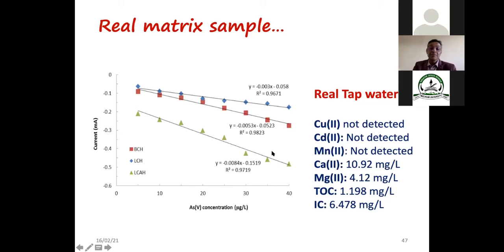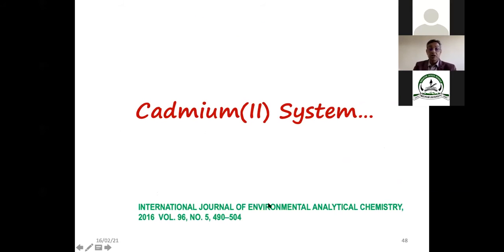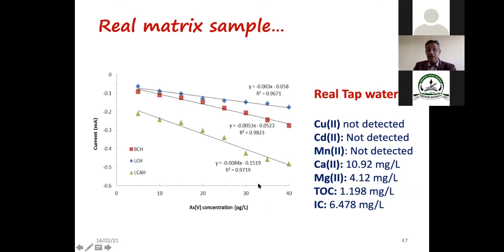If you see, the R square values are 0.98, 0.97, 0.96 like that. So a very good correlation was obtained, whether we have used the organically modified bentonite, the local clay, or the organo-inorgano hybrid material LCAH. This data was published in Electroanalytical Chemistry, and you can see that the method is applicable to real matrix samples also.